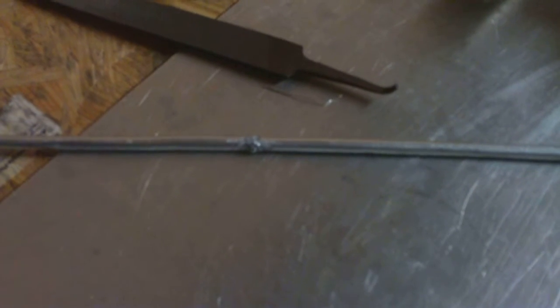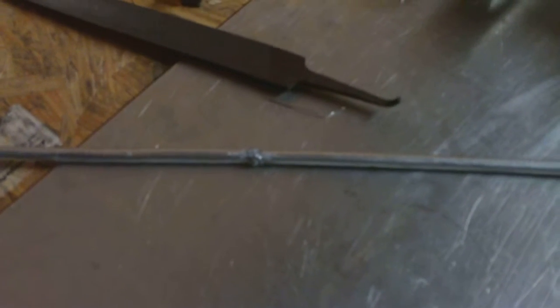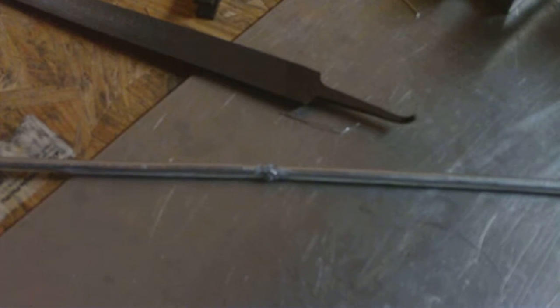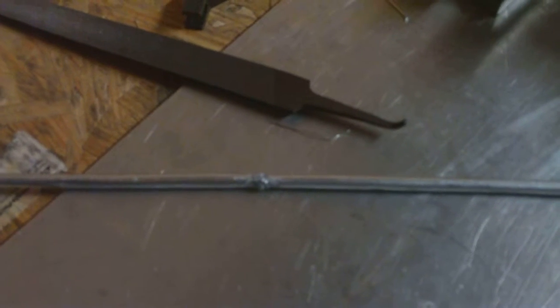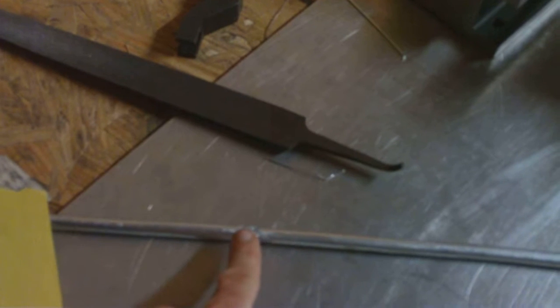Here's what I learned, and this is probably going to sound really basic to other welders who have been doing this for a while, but something that really helped me out was understanding the frequency and how important it is. High-frequency is going to give you a narrow arc so you can get into really tight areas. But for this butt welding, this small aluminum tube, that did not work for me. Any little bit of gap between the end of the two work pieces that you're butting together, that arc does not want to stay in the middle. It's going to either hop to your right side piece or it's going to hop to your left. It's not going to go down the middle.